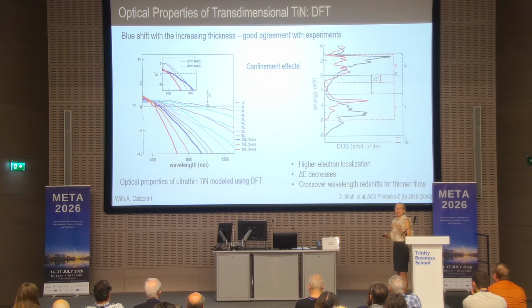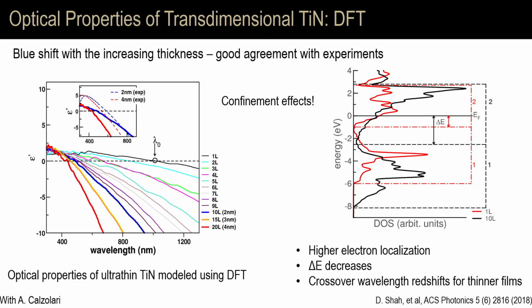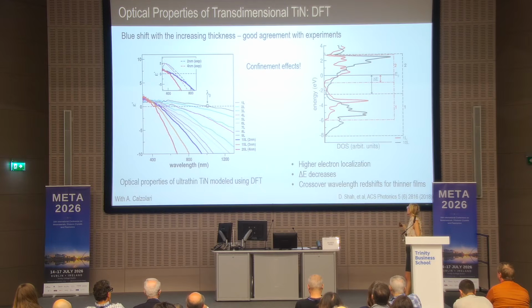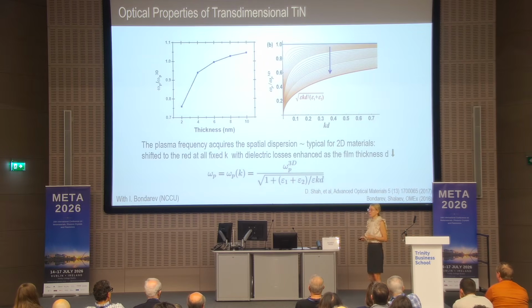so that again your materials become less metallic when you go to a thinner film, and that can actually be well understood in simple terms. When you have your bulk material with, let's say, high carrier concentration, if you thin it down, then when you're calculating the carrier density, it would be inversely proportional to the thickness. So you actually acquire this dependence on the thickness that you don't have in conventional thin films. And we also showed that in thin films you have a band structure change, and that also drives the change in the optical response.